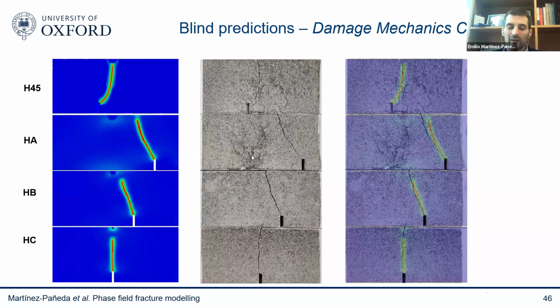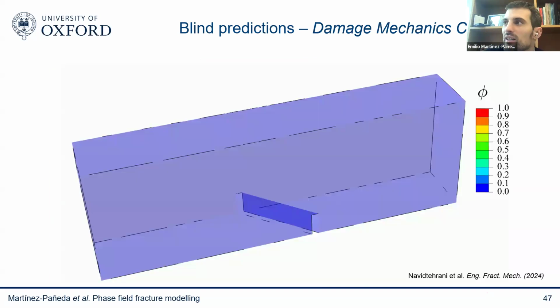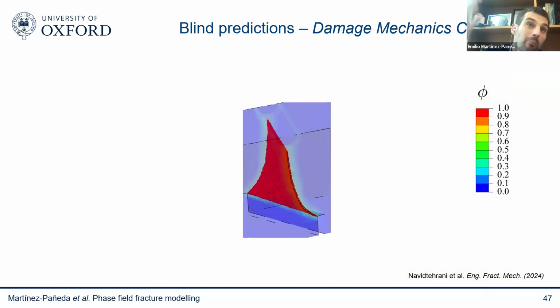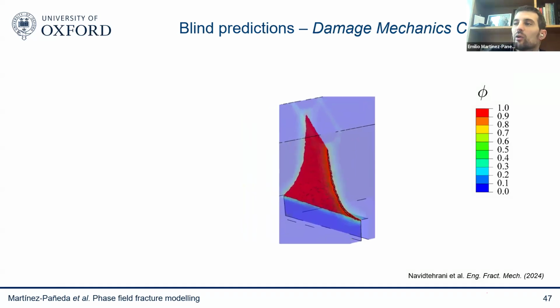And then finally, they did one case in the XCT scan. So they have a full 3D representation of the crack morphology. And they said, okay, those of you that are brave enough, do a 3D calculation and tell us what crack morphology you get. So this is what we did. This is the calculation of 3-point bending. The crack is tilted. You can see how the crack grows, the whole crack surface going all the way through. And then we compare that with the XCT image that they had, and the agreement was very good.